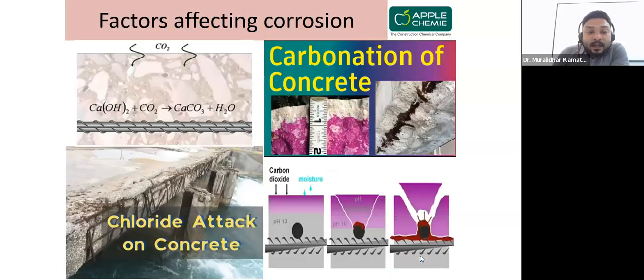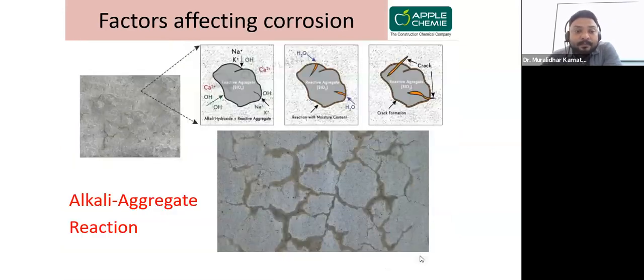Okay. Again, you can see these are the factors affecting your corrosion. This is carbonation of concrete. Generally, a phenolphthalein indicator is used so that you can check. You see the pH dropping from 13 to 10; when it is going to initiate, at that time you will find the concrete is going to deteriorate. Here it is exposed to chloride attack and carbonation attack, and both are factors affecting your corrosion.